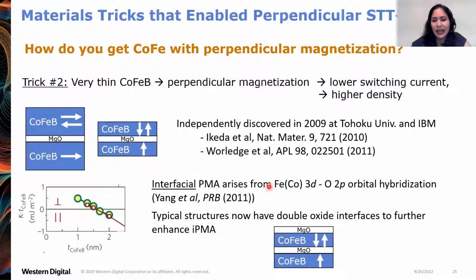Okay. And in fact, conventional STT-MRAM structures now put an MgO cap layer at the top. So you have the cobalt iron boron free layer on top of a MgO barrier with an MgO cap. So then you have interfacial perpendicular magnetic anisotropy generated from both interfaces to further enhance this effect.